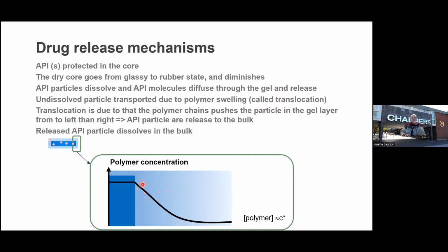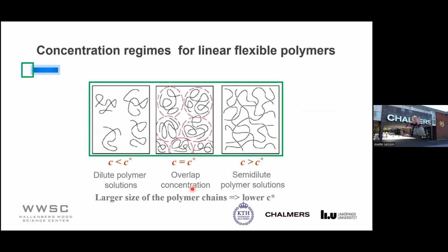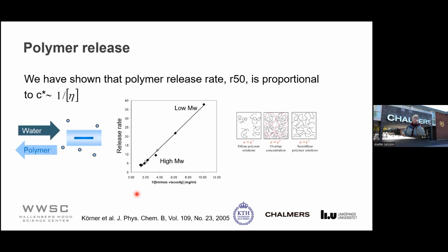And now we can see that the thickness of the gel layer is very important, and that is controlled by the overlap concentration. And a thicker gel layer will then give a slower drug release rate. So the overlap concentration is a very important parameter. So you can tune the drug release rate by changing the molecular weight of the polymer chains. So we were actually the first ones that were able to show that the release rate for polymers was depending on the overlap concentration, proportional to the overlap concentration. So we determined the intrinsic viscosity, and 1 over the intrinsic viscosity is proportional to the overlap concentration. And here we can see that we got a quite nice line.